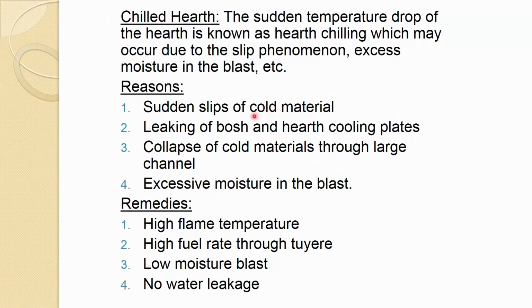So, reasons are sudden slips of the cold material, leaking of bosh and hearth cooling plate, that is also very important, and very often it happens. Collapse of cold material through large channel, excessive moisture in the blast. If there is excessive moisture in the blast, then the temperature reduces, which also results in the chilling of the hearth. Remedies: high flame temperature one should have, high fuel rate through the tuyere, low moisture blast, no water leakage, so properly sealed. These are some remedies of chilled hearth.